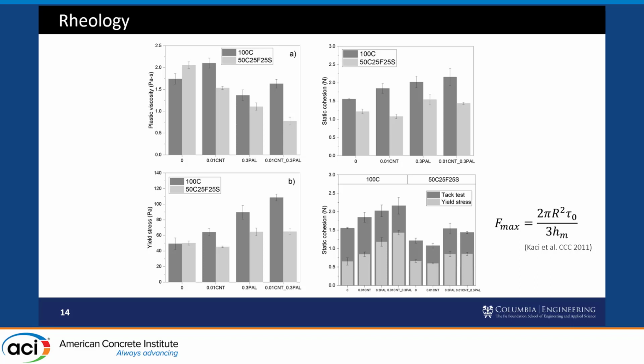And so you'll notice that the trends are similar, which is good, but the measurements through shear rheology are much lower, and that is likely because we know better now. We should have used static yield stress versus dynamic yield stress because that would be more closely tied to cohesion, and in that way that should bump up the values more. But in any case, the trends are similar.